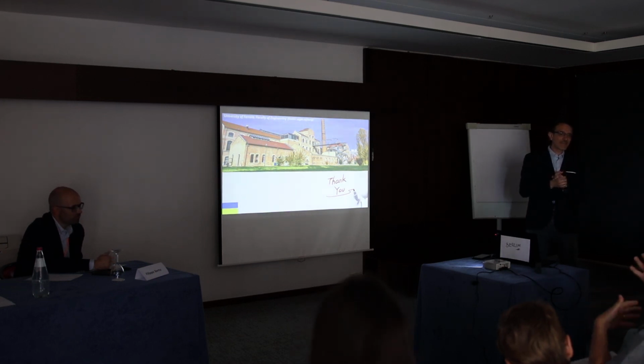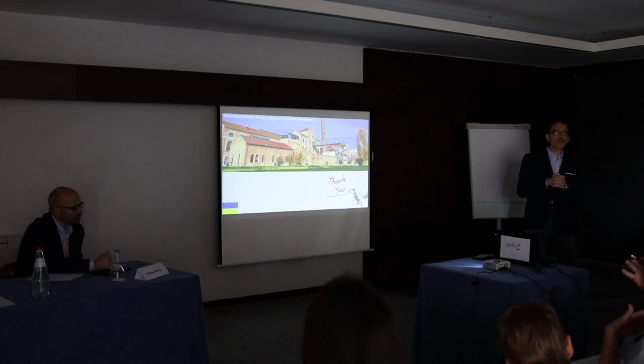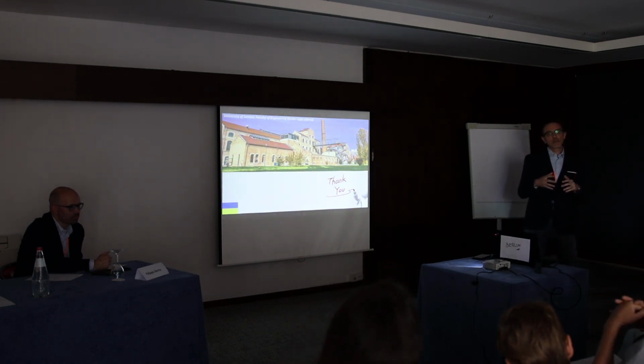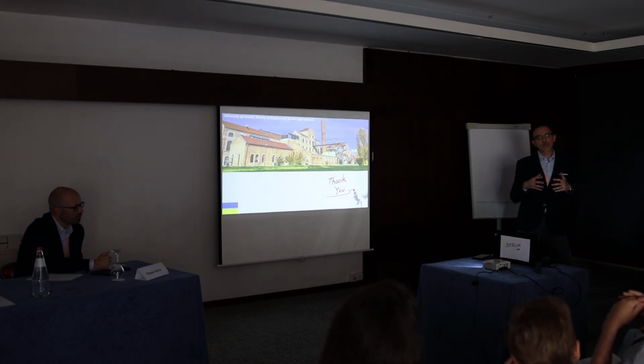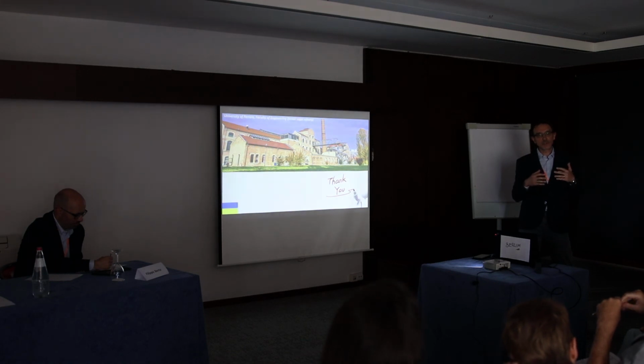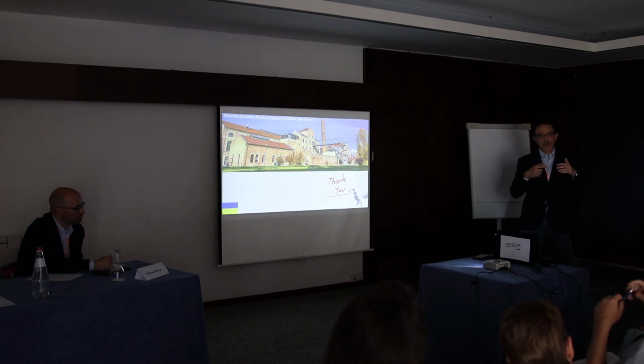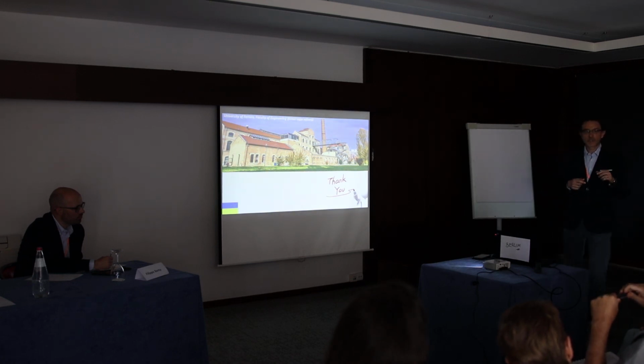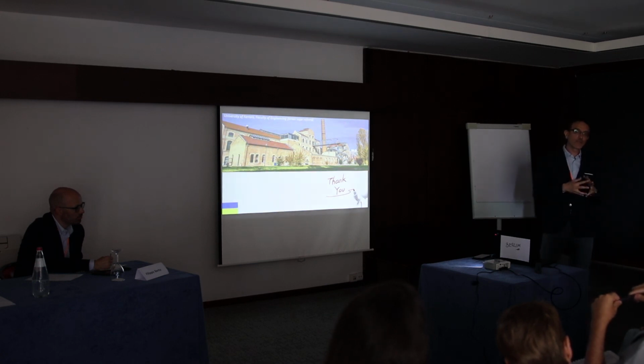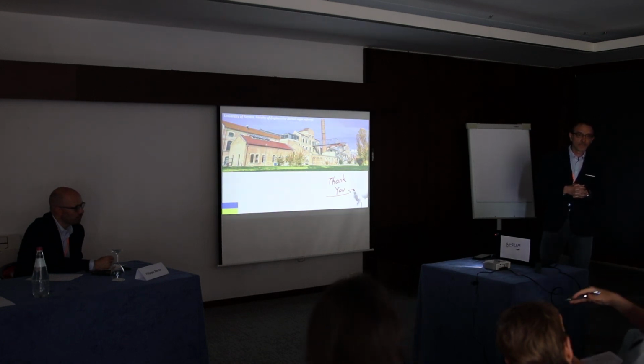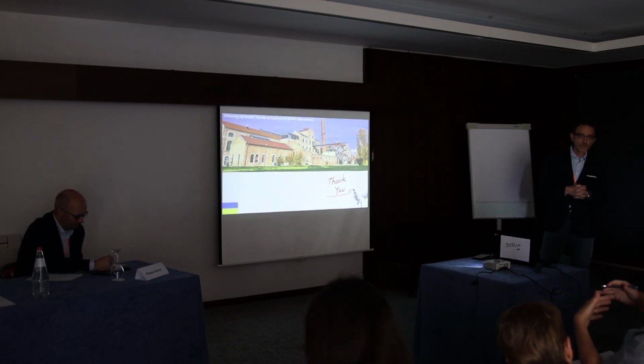So basically, you're comparing two rather different materials. It's not just the manufacturing process, but there are other aspects as well. Yes, of course, for the additive manufactured material, the manufacturing process is different. So you maybe have a higher cooling rate because you are adding material at each layer. So maybe this gives a smaller grain size, so this may increase the yield stress compared to the raw material. It would be interesting to see how they perform when the raw material is also perhaps heat treated to achieve a similar microstructure. But this is another story.